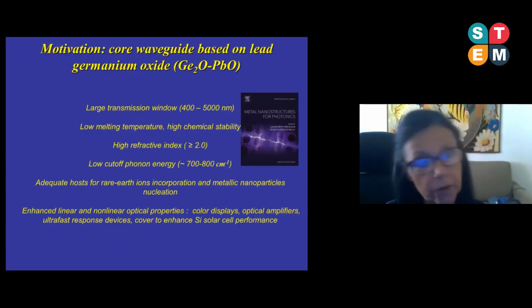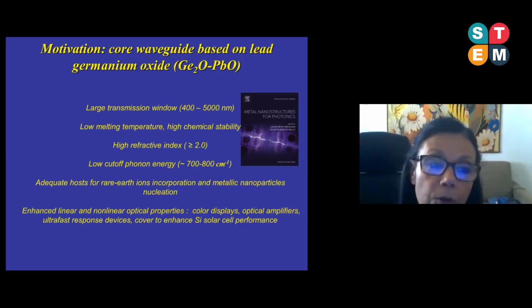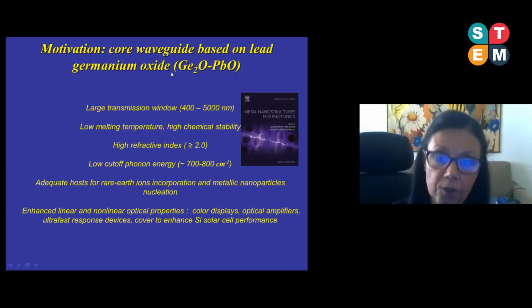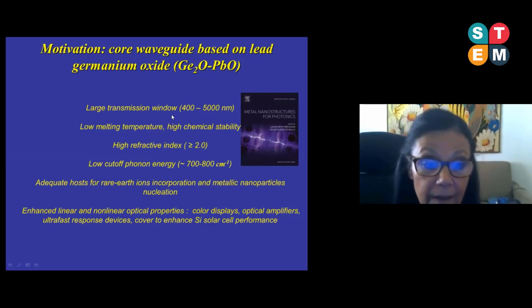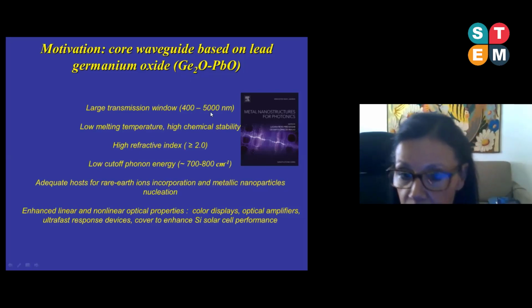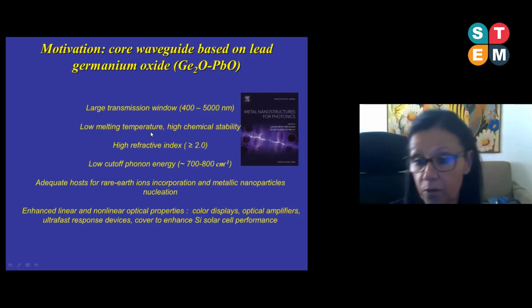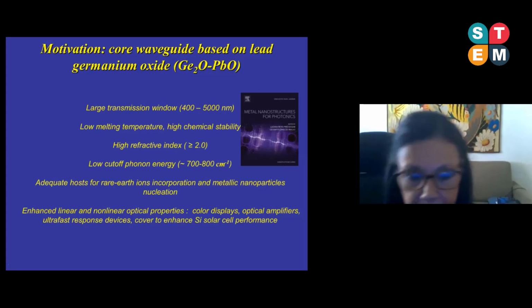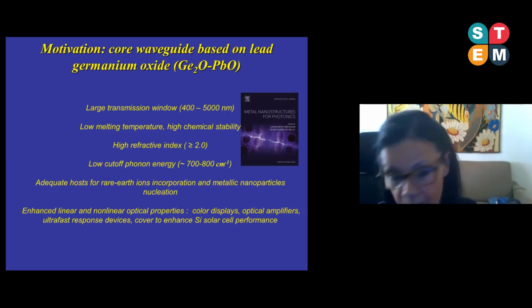Although my talk will focus on waveguides decorated by islands of gold nanoparticles, I'd like to briefly show you the motivation for the use of this material. They exhibit a large transmission window from visible to near infrared to mid infrared, low melt temperature with respect to silicates to borates, high chemical stability, normally high refractive index around 2 or more, low phonon energy with respect to borate and phosphates, and this represents an important characteristic because it provides low non-radiative losses, an important feature for the upconversion process.